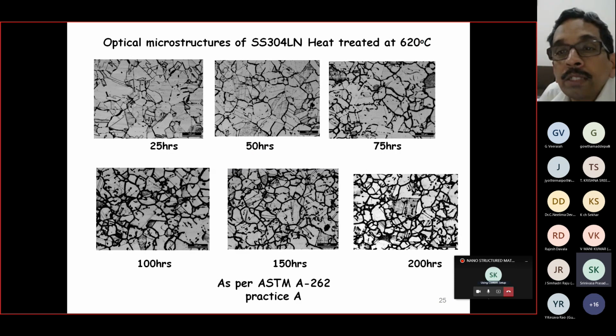So for that, what we did was, we did an optical microstructure. My friends from metallurgy can see that basically these are all austenitic materials and this is the grain structure at different hours of heat treatment. You can see that the grain boundaries are quite thick. That means at the grain boundaries, the chromium carbide precipitation has occurred.